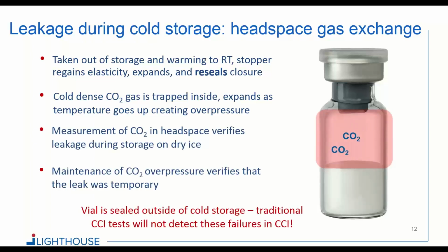So how do you detect this? Well, if you can measure the carbon dioxide in the headspace, that would verify that the vial had CCI issues in the cold storage. And if you actually measure over time, if this overpressure of CO2 is maintained, then you can also verify that these leaks that we see are temporary. And that was an important discovery in the early stages of investigating this phenomenon, because what that means is the vial is sealed outside of cold storage, so traditional CCI tests will not detect these failures in CCI. So again, you imagine taking a vial at room temperature that is thawed and you do a blue dye test, it's actually sealed.